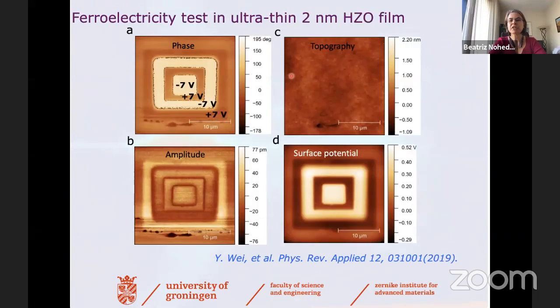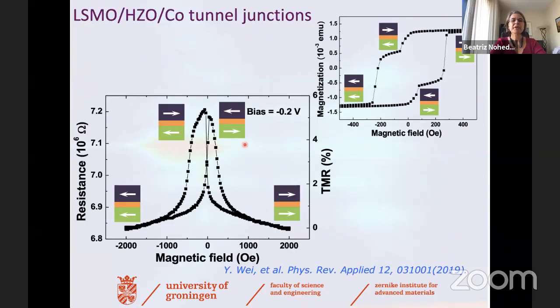These ultra-thin 2 nanometer films are still ferroelectric. They still show the typical characteristics of ferroelectric switching in the material. And when we put them in between these two ferromagnetic electrodes, we can measure the TMR effect in these materials. And you can see very nice low noise TMR loops, and the magnetization that corresponds to the switching of the different layers.